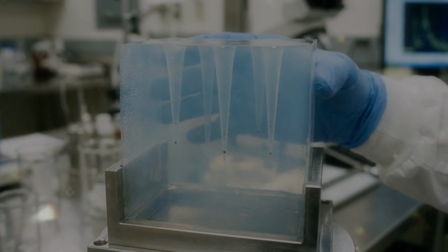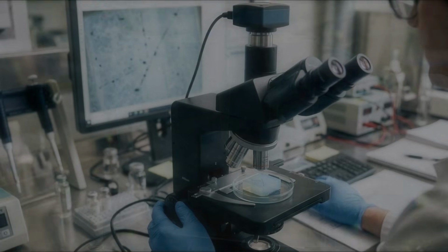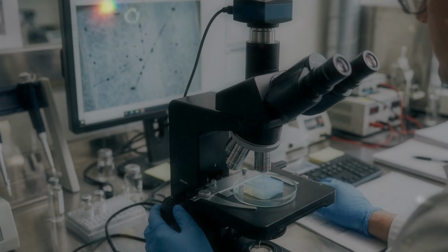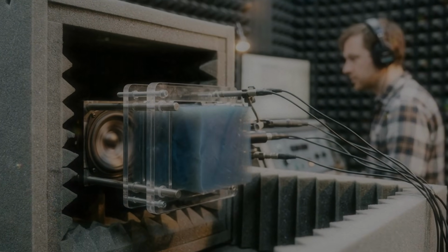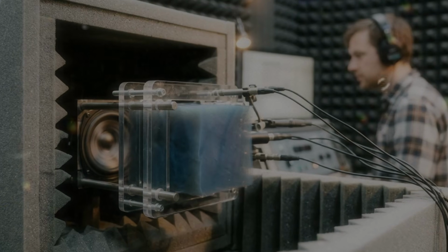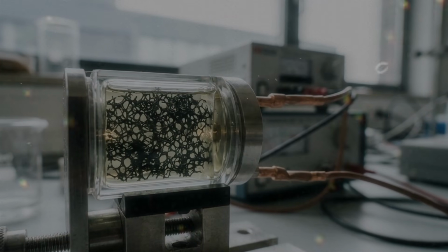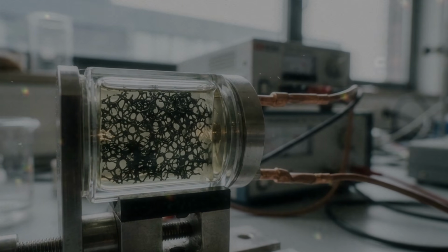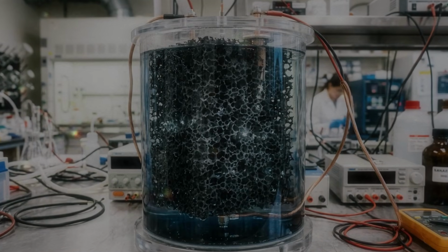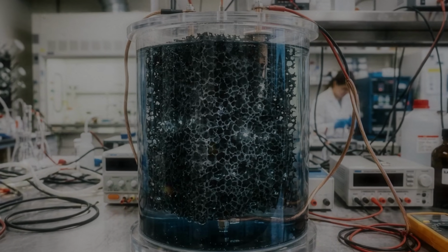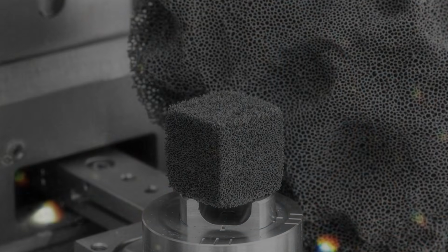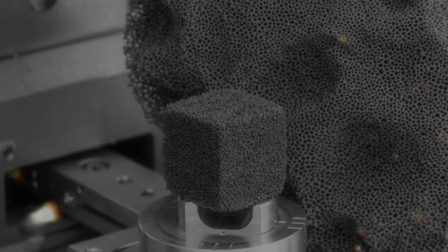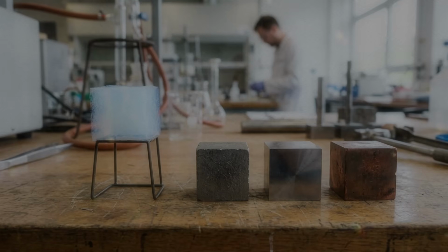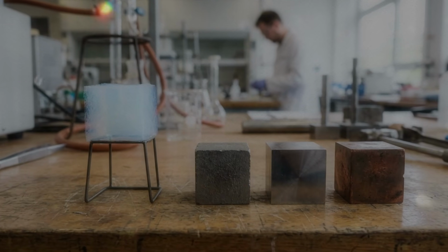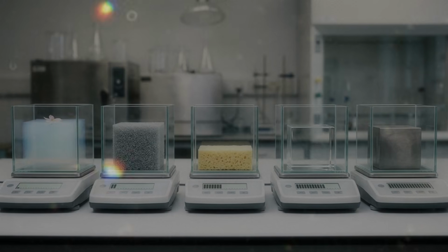The change can happen quickly or slowly depending on the ingredients, temperature, acidity, concentration, and preparation method. A mixture may remain fluid long enough to be poured into a mould, then gradually become firm. In other cases, the reaction moves so quickly that anyone working with it must be ready. Chemistry, like a cat near an open cupboard, does not always wait for permission. The mould determines the general shape of the final aerogel. A scientist might prepare a thin panel, a cylinder, a small bead, a blanket, or a sample designed to fit inside an instrument. The gel can also form around fibres, particles, or other supporting materials.